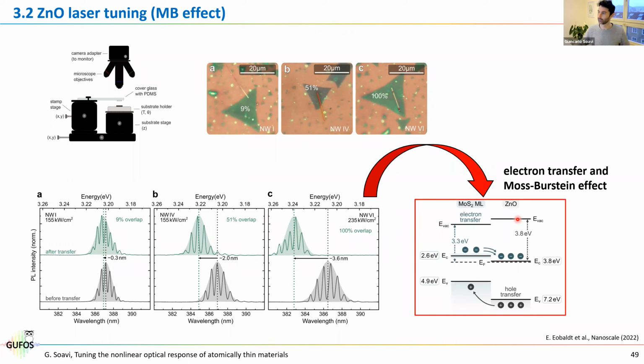In particular, when you do XPS measurements, it turns out that MoS2 and zinc oxide form a type 2 heterostructure, where you have electron transfer from the MoS2 to the zinc oxide. And when you have an increase in the electron density in the zinc oxide, you have the so-called Moss-Burstein effect. That is basically an opening of the gap and a blue shift of the lasing threshold. So we can clearly tune the lasing by changing the overlap due to this Moss-Burstein effect.